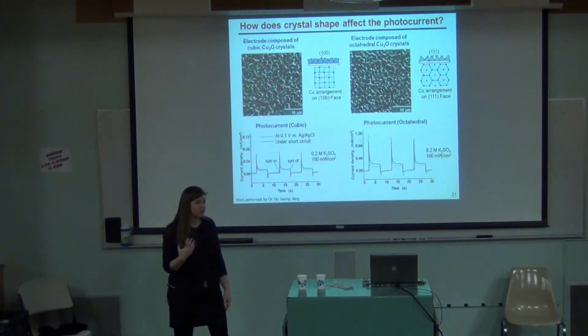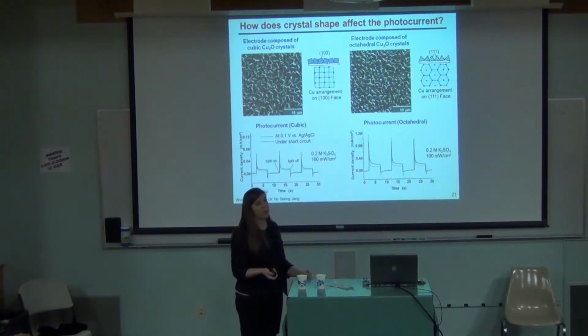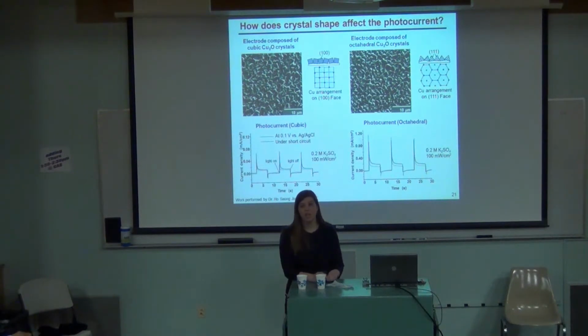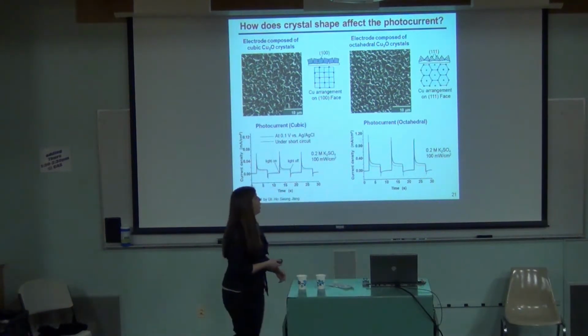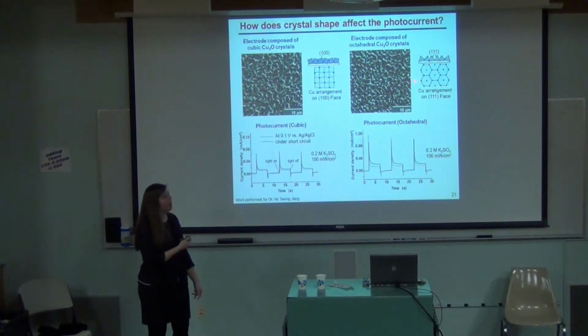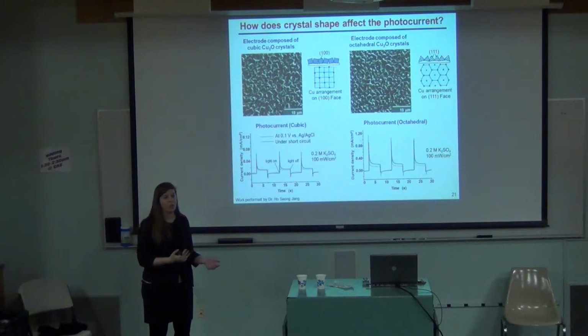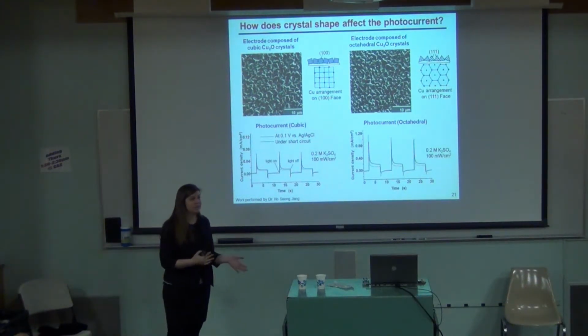Now, neither one of these materials are earth-shattering. The 0.2 would be about 0.2% efficient, which is not really... When you think about efficiency, you want better than 0.2%. But we're making progress because we've already had a tenfold increase from having cubic to octahedral. So now there's hope, because what if these could be improved by making them smaller? Or what if they could be improved by making them a slightly different shape? Or what if we could improve it by pairing it with another material and putting a catalyst on it?